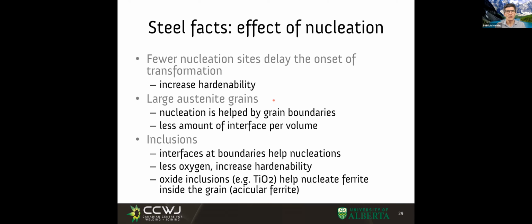And remember we talked about manganese and silicon as ways of taking oxygen out of your weld. Now, if you take all your oxygen out of your weld, you don't form this titanium oxide and you don't nucleate this ferrite that is so beneficial. And you may end up with a weld that has a pretty poor microstructure and pretty poor properties. Isn't this interesting? Typically, you don't like oxygen. But zero oxygen in welding is not your friend either. Not in steels.